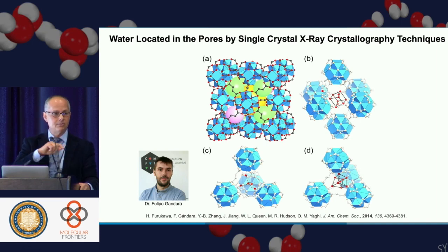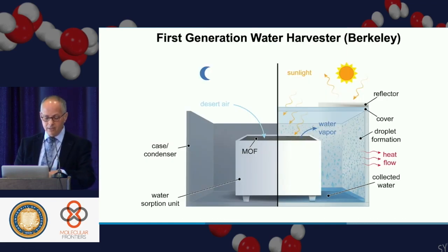Because if you have a distribution of those adsorptive sites, because your material is amorphous with many different adsorptive sites, you will get a shallow isotherm, and you will not get a very good, efficient material. Okay, so that MOF, we scaled up to kilogram quantities, and we did exactly what I would have done in